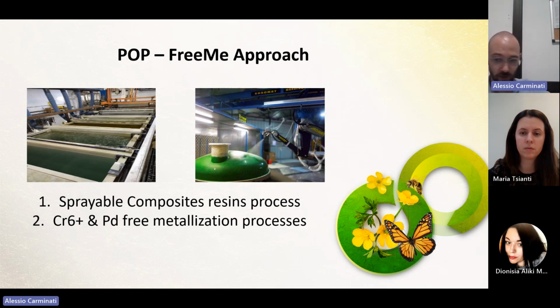This kind of resin will be composite and will include some metal particles or particles of a salt of a metal that will do the same thing as the palladium does, so the activation of the surface. And the etching step in this kind of approach is not present, just because it's substituted by the resin.